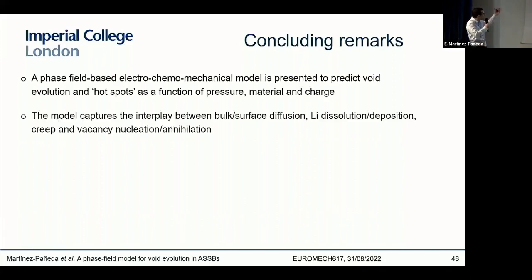We try to make the model as mechanistic as possible, incorporating all the phenomena that we think govern this process: the annihilation and nucleation of vacancies, the substitutional lithium diffusion, the creep and lattice distortion, and so on, and the reactions happening at the interface. That allows us to capture the interplay between bulk and surface diffusion, lithium dissolution and deposition, creep, and vacancy nucleation and annihilation. So we can see the relevant weight of each of these phenomena.